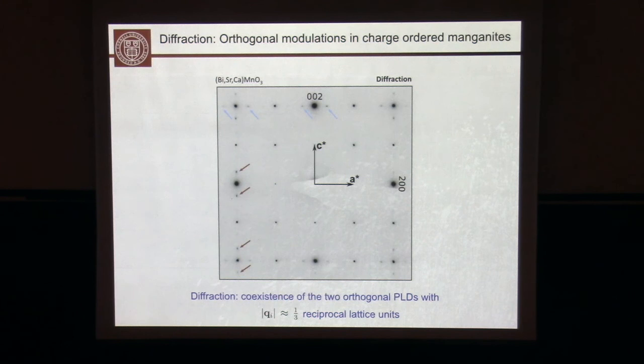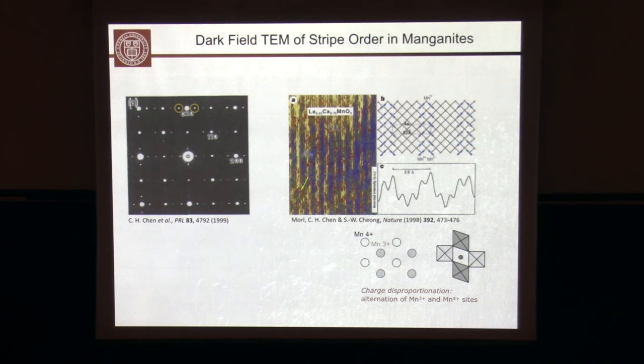OK, so we are not the first ones to look at this. There's been work in the 80s and 90s, also using cryo microscopy, where they used the diffraction pattern and imaged only with those electrons that come from the superlattice reflections. And that led to the picture of stripes. So here is lanthanum calcium manganite in stripe order that was observed using these reflections, which raised many questions.